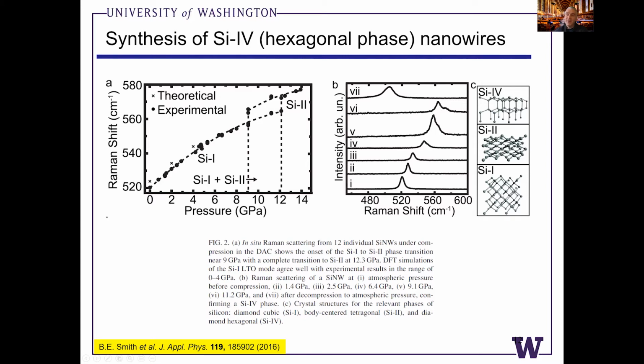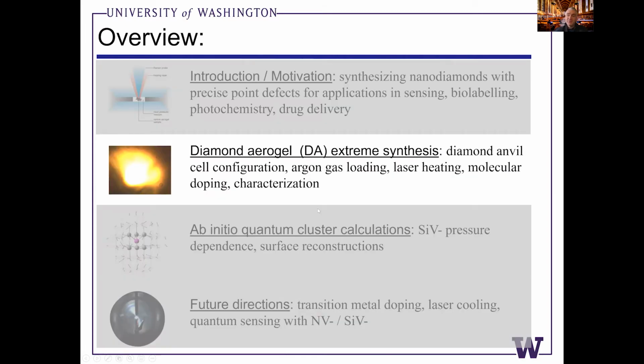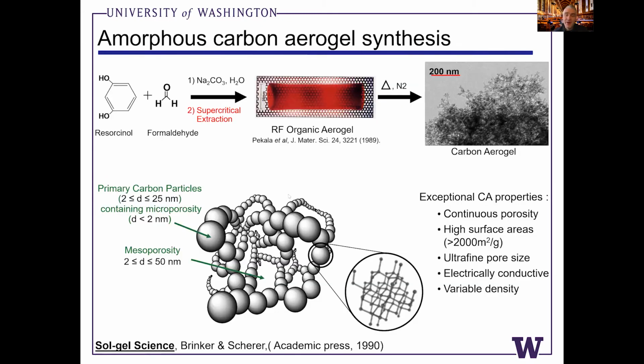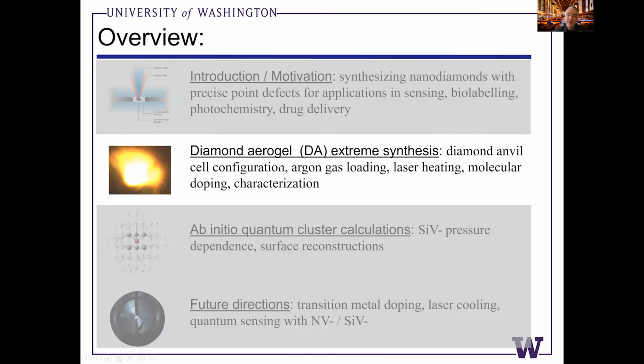And this is a really amazing phase transition, because you go from a material that has an indirect band gap to a material that has a direct band gap. This is a very surprising electronic structure property change that you can reach with pressure. Just to illustrate some of the other neat things you can see with pressure. As you squeeze the crystal, you can see the Raman spectrum blue shift. You can see both the frequency of the cubic Raman spectrum change, and new phases arise with their own unique Raman spectra. So I'll refer to this later on a bit in the talk. So what I'd like to do next is talk a bit more about the synthesis methods we use in the diamond anvil cell.